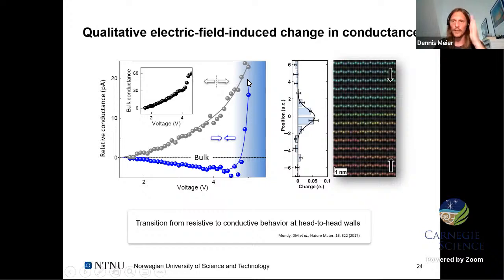This is where the electrons, which are sitting at this inversion layer, are contributing to the conductivity. And you can even see in these nice EELS measurements from Julia on the right-hand side that, at the head-to-head walls, right at the position of the domain walls, manganese changes the valency going from 3+ to 2.8+, which converts into a certain electronic charge. And these electrons accumulate at the head-to-head walls for screening, and it confirms this bending model that we locally have electrons. And by driving the system with a higher voltage, we can then go from insulating to conducting.